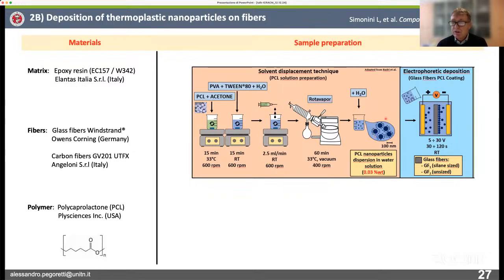And then we use this solution containing negatively charged polycaprolactone nanoparticles by using electrophoretic deposition, which is a technique I already mentioned before. And with this technique, it is possible to force the charged particles to migrate, to move on the surface of the glass or carbon fibers.